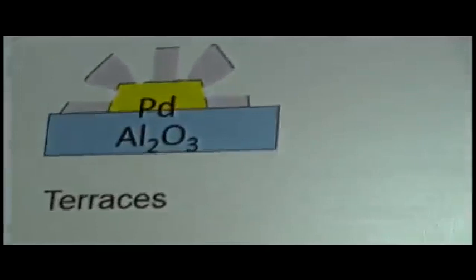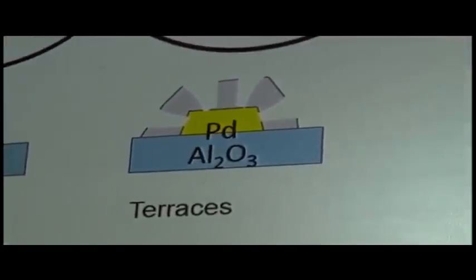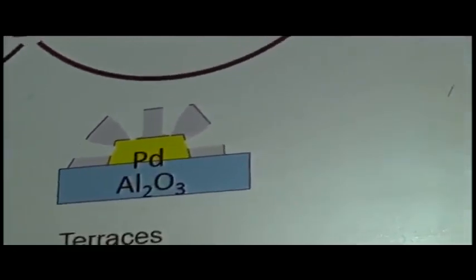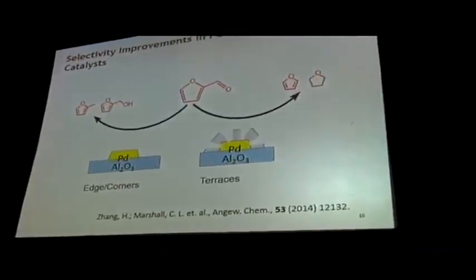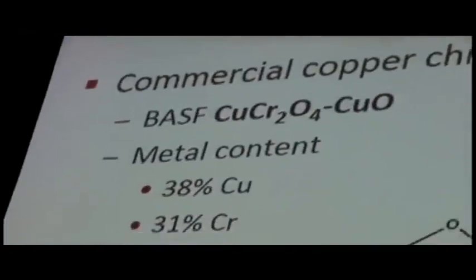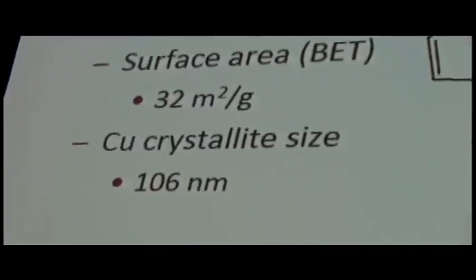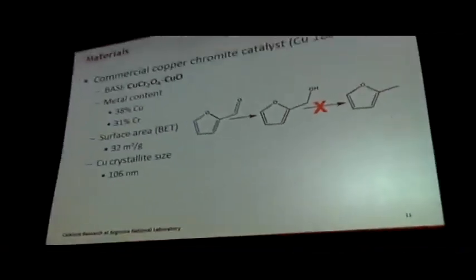By putting in the ALD overcoating, that ALD overcoating for alumina in this case goes primarily to edge and corner sites, leaving terrace sites open and giving rise to higher concentrations of the furan products that you see on the right there. So, the catalyst I'm going to be talking about in this morning's talk is a copper chromite catalyst. It's a commercial catalyst. It comes from BASF. The concentrations are shown here, relatively low surface areas, and it's quite selective for the reaction of furfural to furfuryl alcohol.